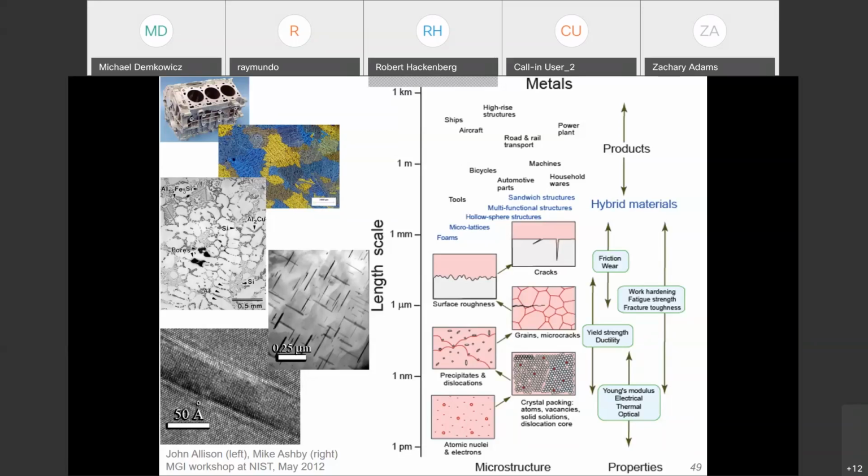And there are various techniques. I was mentioning the as-cast structure. This is really coarse. This is half a millimeter, 500 micron bars. So these dislocations could blow through the weak part and never really get strengthened by the strong part. Now, as-cast is good enough for a lot of applications, and it's favorable because of economics, because with wrought processing you pay a lot more, but you get a lot more for it as well. So we have all these techniques which are helping feed the modeling and theory efforts, but linking these length scales is the grand challenge, and we still struggle with that today.